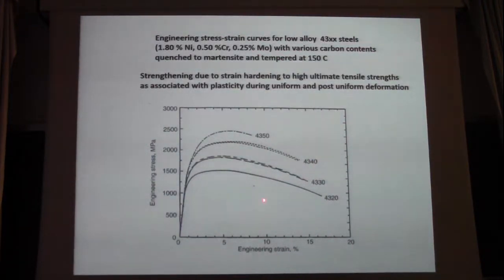Here is a set of engineering stress-strain curves of 43XX steels, XX meaning various carbon contents, 0.2, 0.3, 0.4, 0.5, and tempered at 150 degrees C. And this is a high strength microstructure. And one of the important things here is that the high strength and the high hardness, we talk about martensitic steels, they have high hardness. This is due to the strain hardening, due to dislocations interacting, cross-slipping, increasing in numbers, and causing very high ultimate tensile strengths.